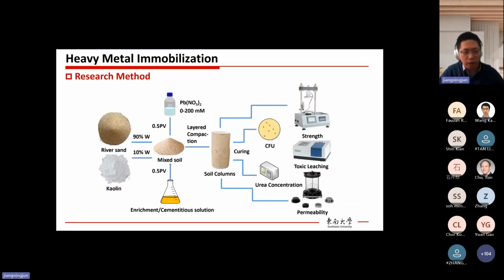Okay, so firstly, I would like to talk about how we prepare the samples. Here we use 90% river sand plus 10% kaolin clay to make the sample. Then it is mixed with a certain amount of lead contaminants. Here we use lead as a representative heavy metal to do the research. Then when we mix it, we use enrichment and cementation solution to do the stimulation. Here we simply use the premix method. It means that we can only do one-time treatment.